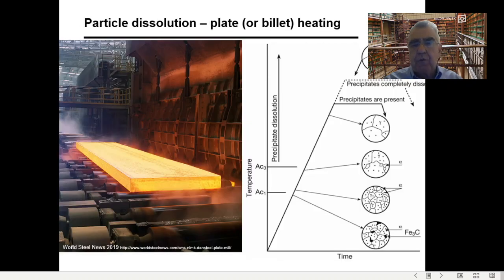So when you go now with the plate into a plate furnace, you're looking into dissolving particles so that you can have mostly niobium and vanadium in solution. Niobium is going to have a nice effect on austenite grain size, and vanadium may precipitate afterwards. And nowadays we are also looking at titanium to precipitate at very low temperatures, like 500, 600, maybe during coiling. So it's really important to understand how much you're dissolving of what.